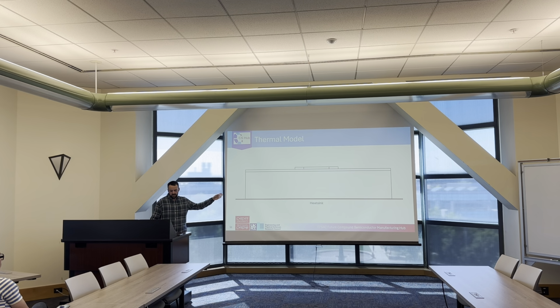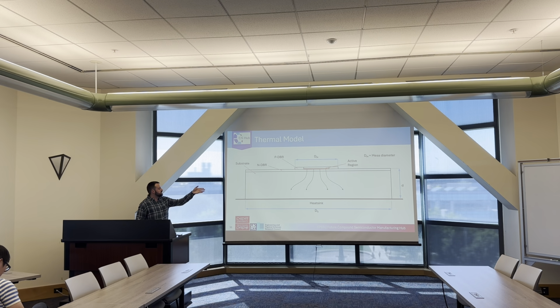This is our device on a heat sink. So we've got the substrate, the DBRs, the PDBR is etched, the NDBR is not etched. So the NDBR is actually grouped with the substrate in this model. Heat generated at the active region with some heat flux to the heat sink. And then the diameter of the substrate is ds, has a thickness d, which also includes the NDBR. And then mesa diameter dm, oxide aperture diameter dox.